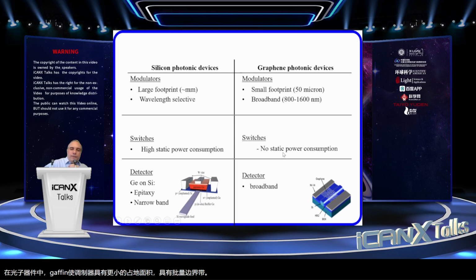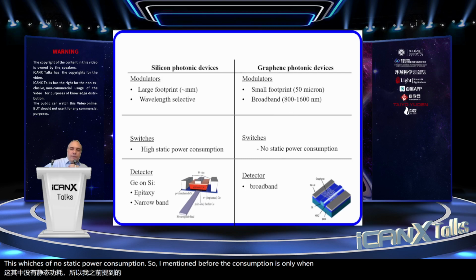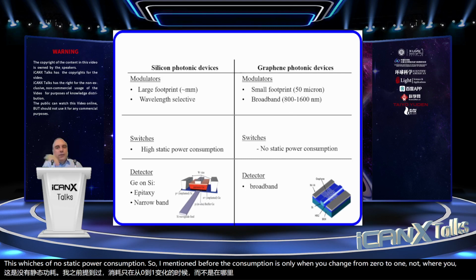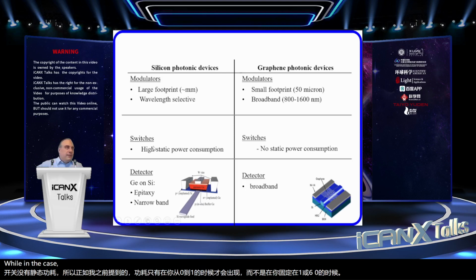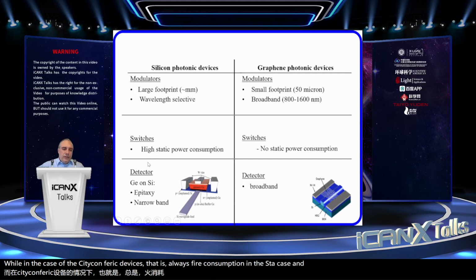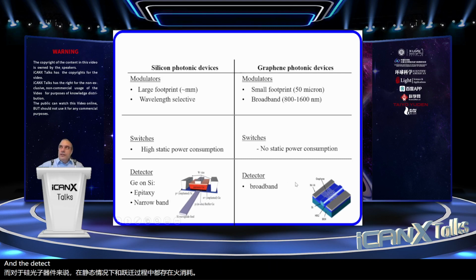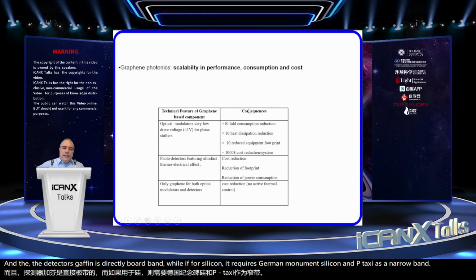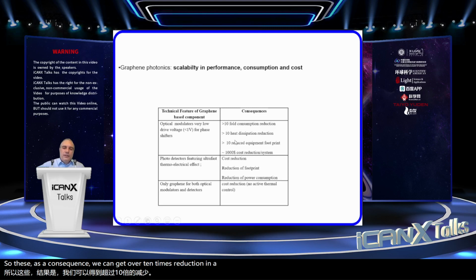The switches have no static power consumption. So as I mentioned before, the consumption is only when you change from 0 to 1, not when you're fixed at 1 or fixed at 0. While in the case of the silicon photonic devices, there is always power consumption in the static case and also in the transition. And for the detectors, graphene is directly broadband, while silicon requires germanium and silicon epitaxy and has a narrow band. So as a consequence, we can get over 10 times reduction in power consumption, in heat dissipation, in footprint, in cost, and so on and so forth.